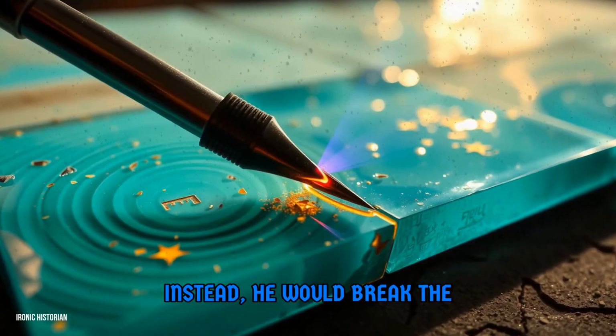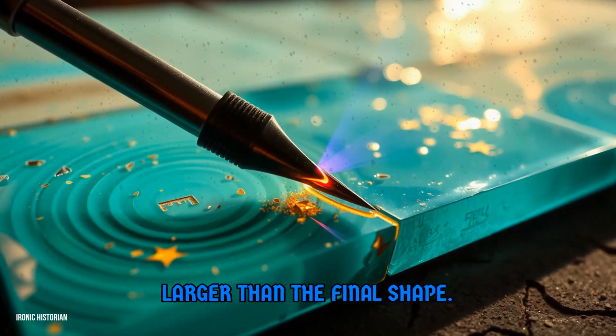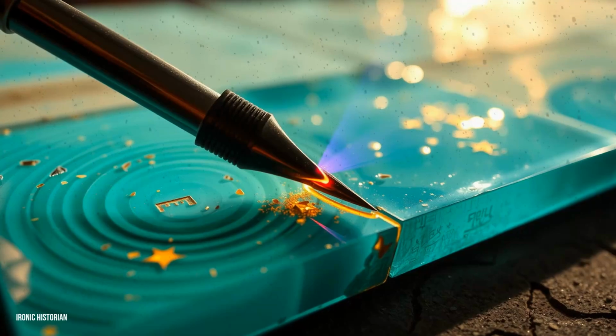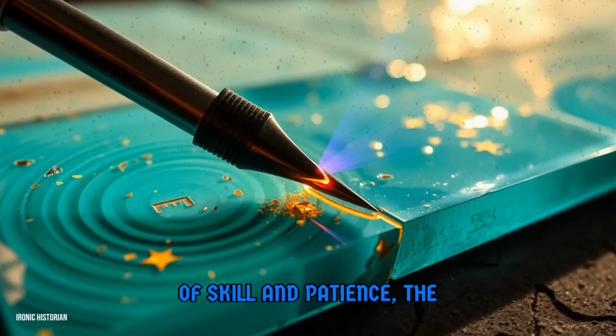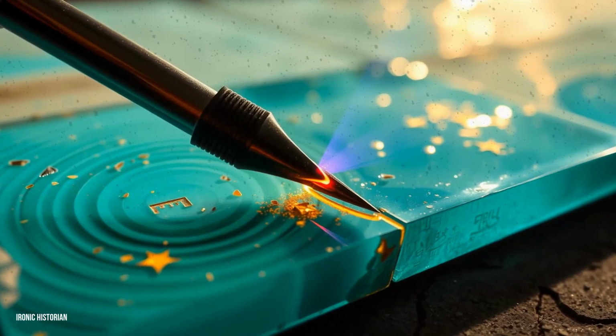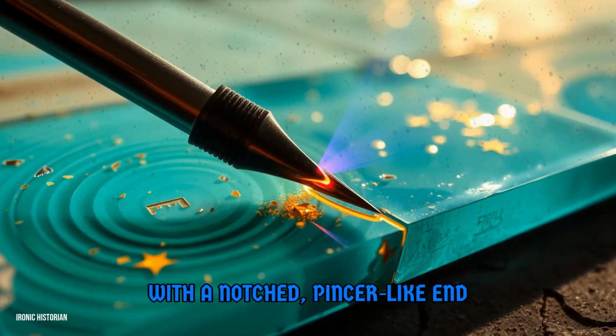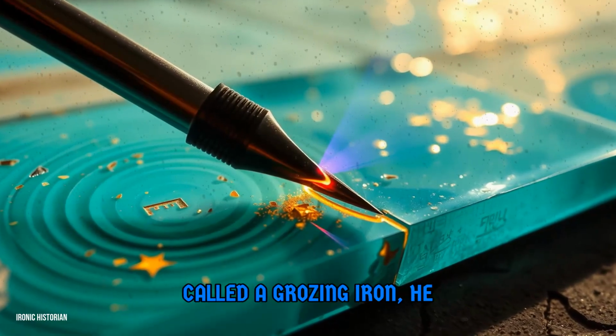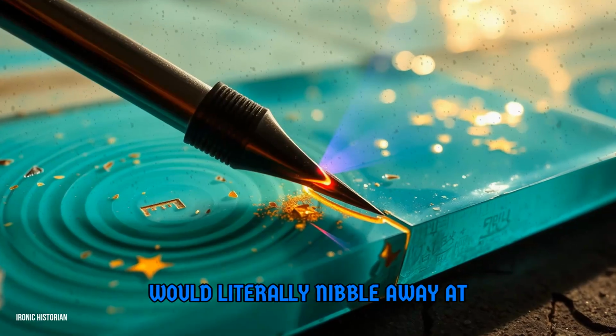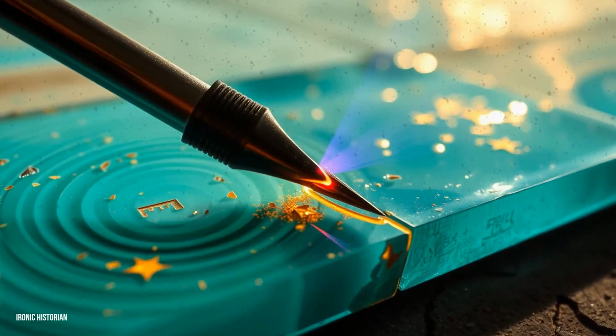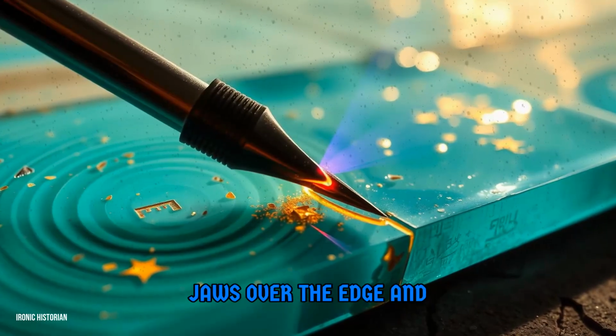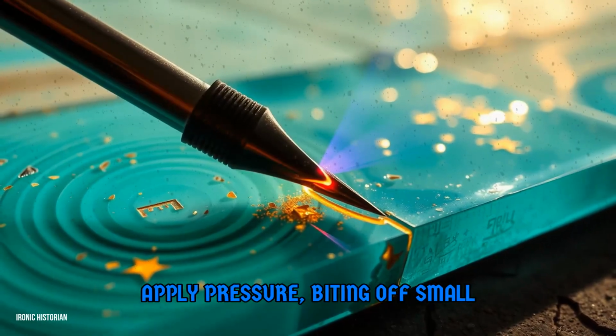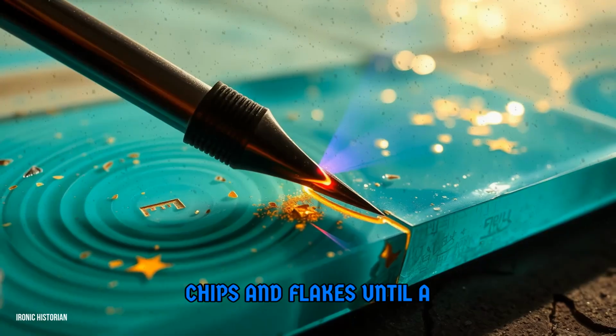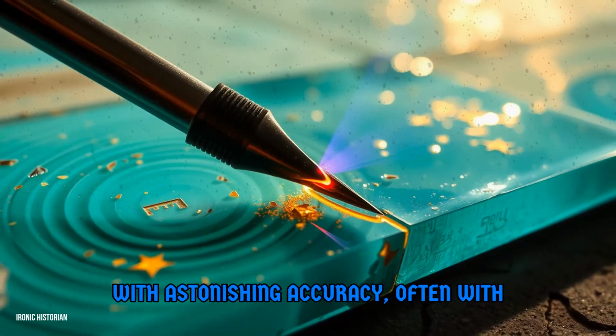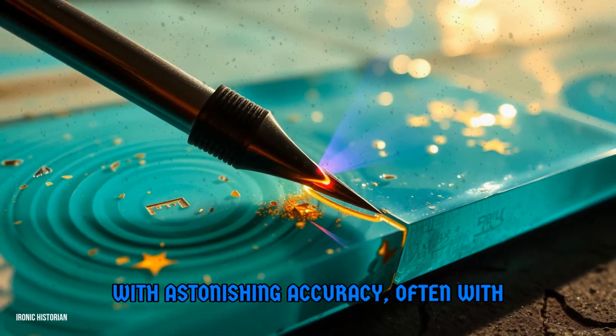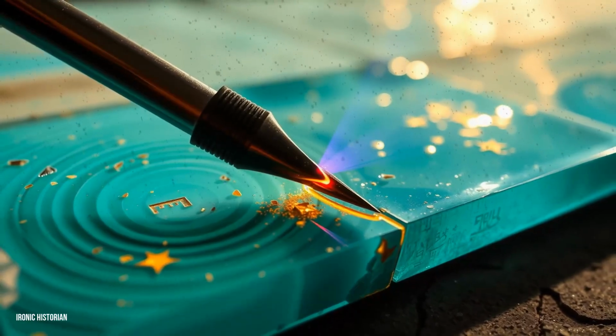Instead, he would break the sheet into rough pieces slightly larger than the final shape. Now came the true test of skill and patience, the grozing. Using a special iron tool with a notched, pincer-like end called a grozing iron, he would literally nibble away at the edges of the glass. He would place the notched jaws over the edge and apply pressure, biting off small chips and flakes until a piece fit the cartoon line with astonishing accuracy, often with a gap of less than a millimeter.